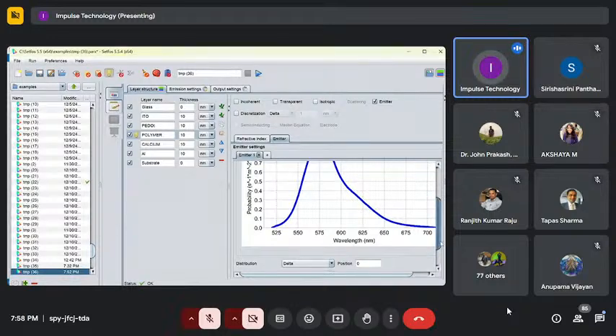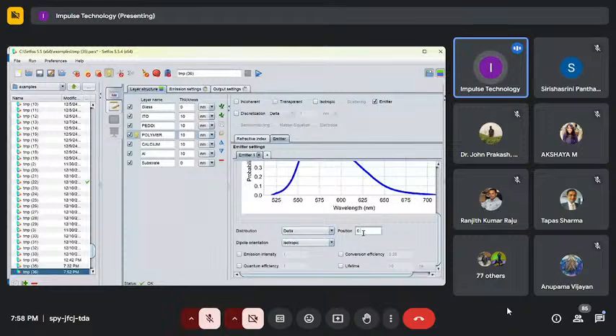You can check the graphs and distributions here. A number of distributions are given: delta, exponential, Gaussian, exciton coupled, absorption coupled, recombination coupled. So you can couple your modules here if you want, and the distributions can be given here. You need to mention the positions and dipole orientations. If you want isotropic, parallel, perpendicular, or custom, you can give it here. Emission intensity, quantum efficiency, conversion efficiency, and lifetimes you can activate as per your choice.